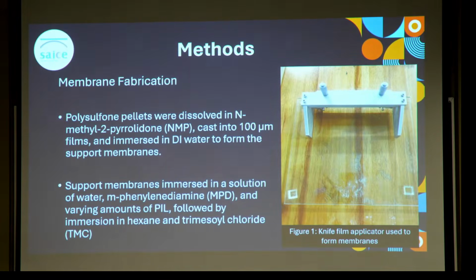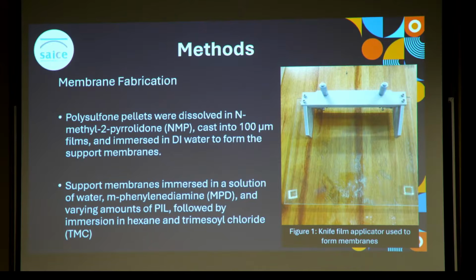To achieve the objectives of the project, the methodology was divided into 3 parts: membrane fabrication, membrane characterization, and performance testing. For the membrane fabrication step, 2 processes were carried out. First, casting the support membranes, and second, forming the polyamide layer, which is also known as the active layer, on top of the support membranes using interfacial polymerization.